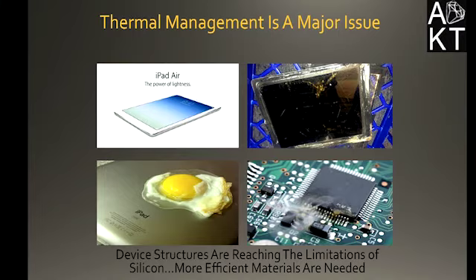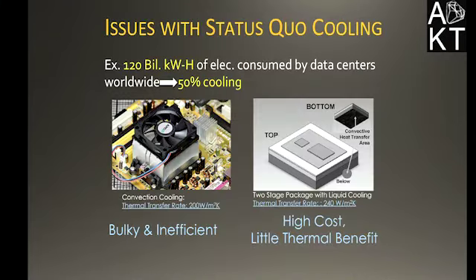And I like to use the example of the iPad because it's the one that most recently exploded in the Apple Store. But a lot of people have noticed this, that if you keep it in your lap, it's very warm. Or if you use your cell phone for a very short duration, it's very hot to the touch. And this is because the thermal management is such an issue, because silicon is very, very heat inefficient. But beyond that, we have issues with the status quo cooling, where in data centers and computing, of approximately the 120 billion kilowatt hours of electricity consumed worldwide, 50% of that roughly goes just to cooling.